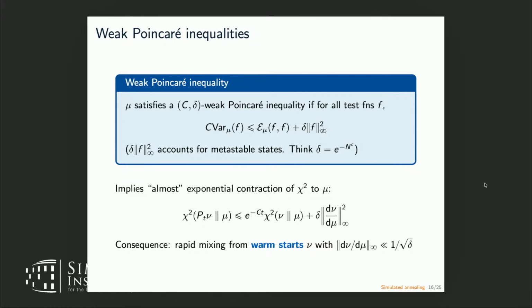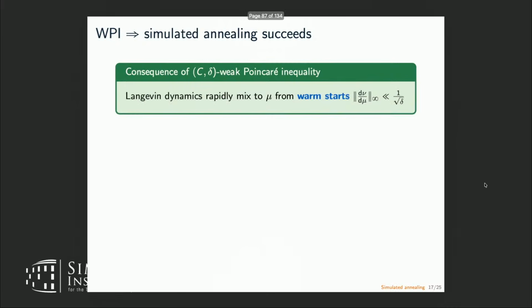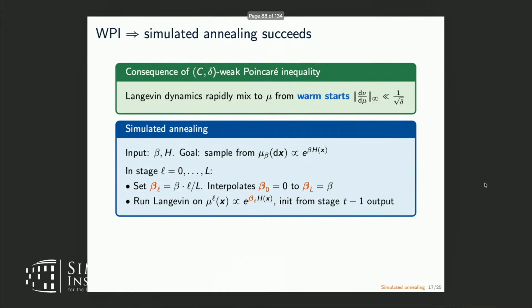And this notion of rapid mixing from warm starts turns out to play really nicely with simulated annealing. So this is how we'll end up showing that simulated annealing succeeds. And roughly the reason is that in simulated annealing, you have a whole bunch of stages, and the measure that you're trying to sample from in each stage is a warm start for the next one. So you get to kind of chain these things together. So recall in simulated annealing, you have these stages. In each stage, you define this effective inverse temperature and run Langevin dynamics on this target measure with the intermediate temperature. Then the point is that each measure in this sequence is a warm start for the next one.